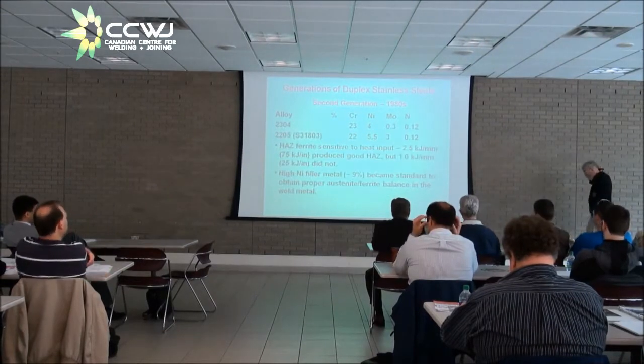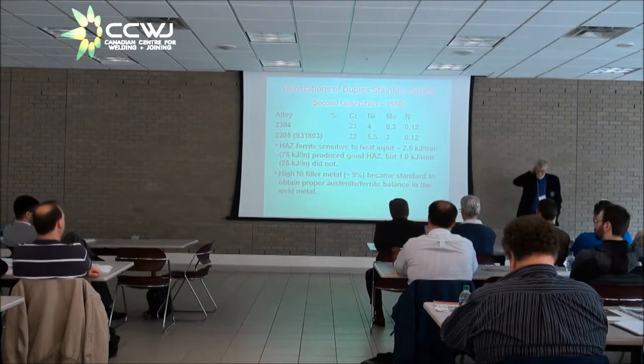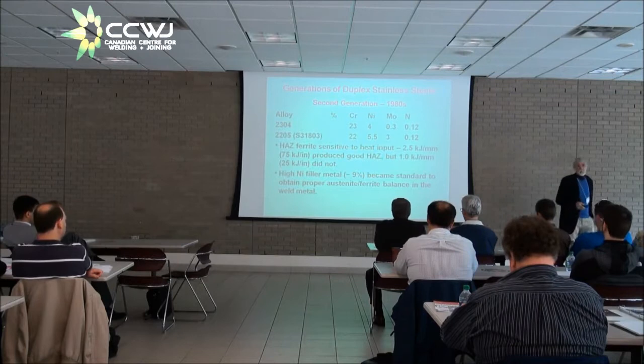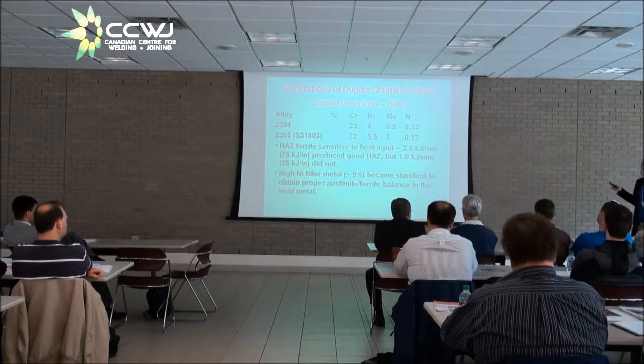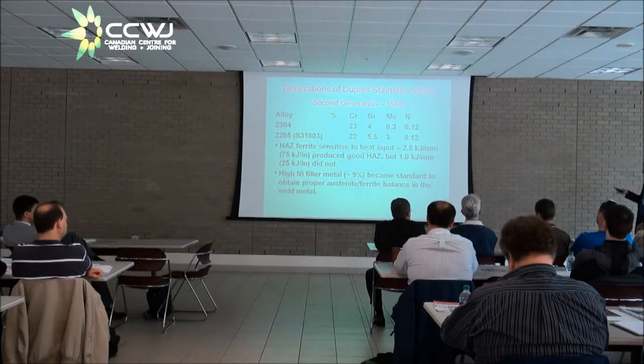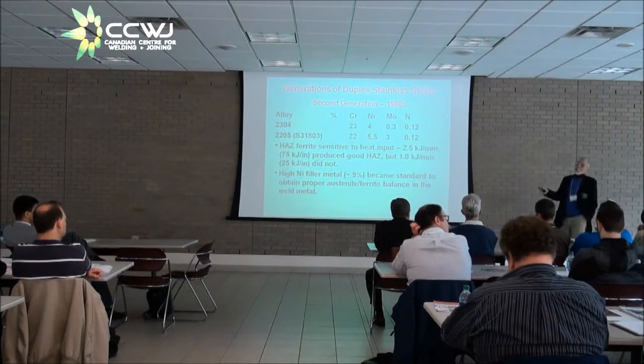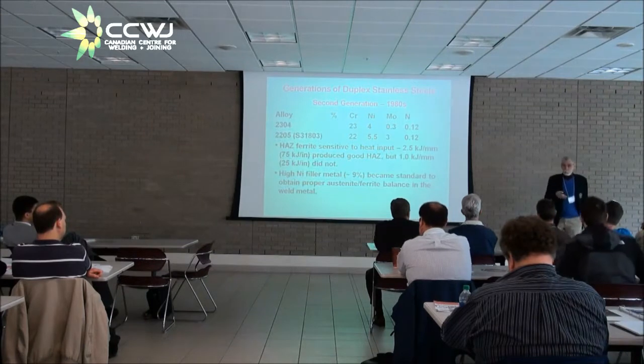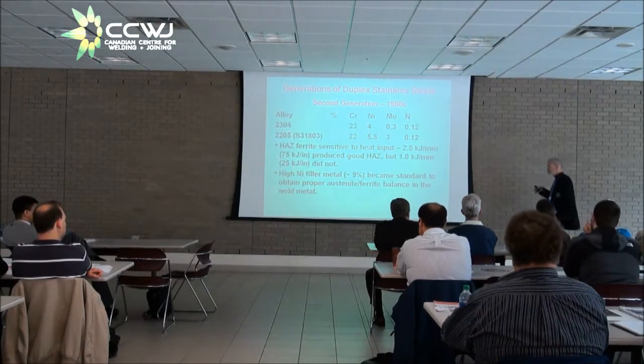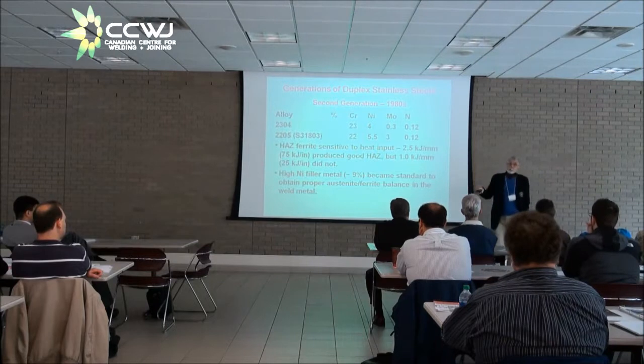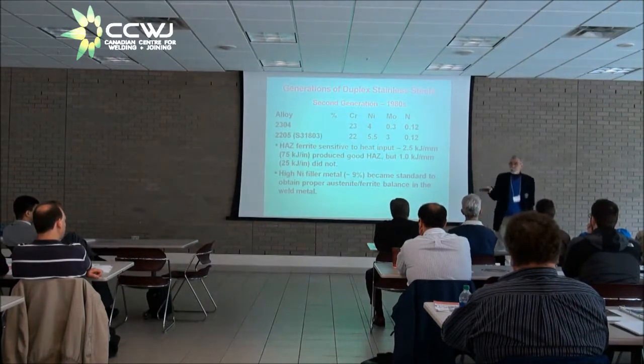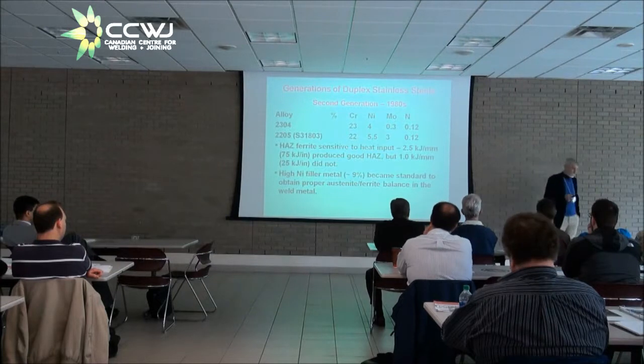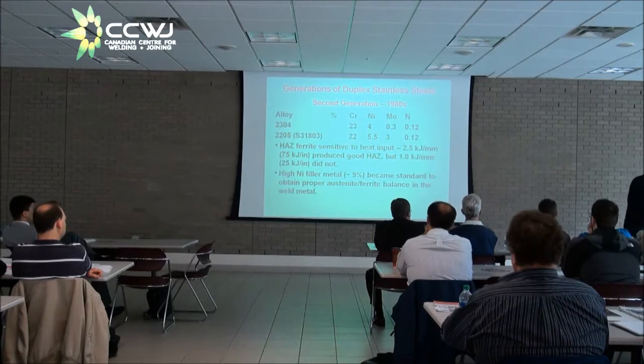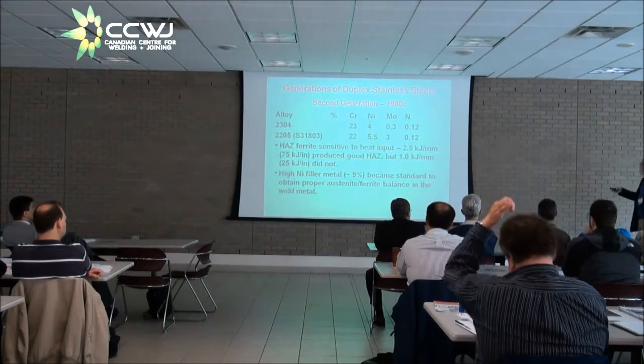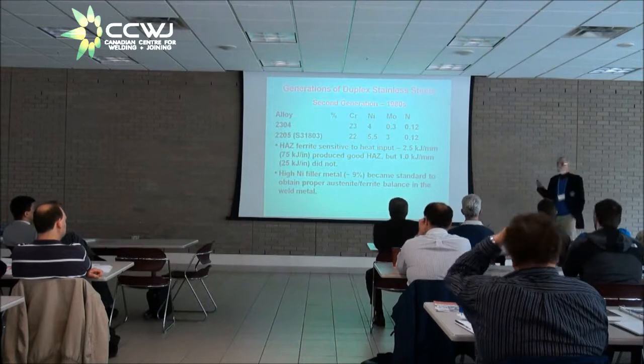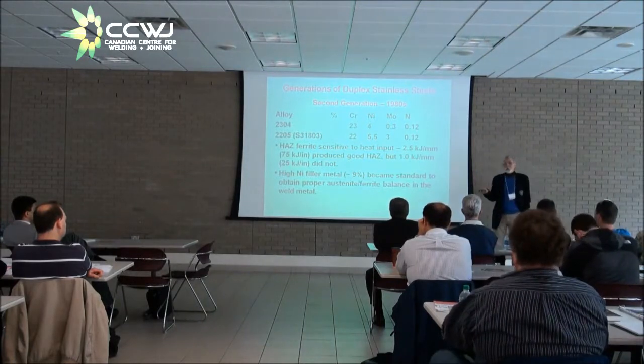Second generation happened by accident, I believe. It happened in the late 70s and became popular in the 80s. The thing that triggered it was the development of the argon-oxygen decarburization system for refining stainless steels. In the argon-oxygen decarburization system, you blow argon with a small amount of oxygen in it into the liquid metal. The oxygen reacts with the carbon, takes the carbon out, and the argon is the carrier to help the bubbles get removed from the melt. But when you read the books about when AOD was developed, what you find out is that people right from the get-go with AOD were using air as a source of oxygen.